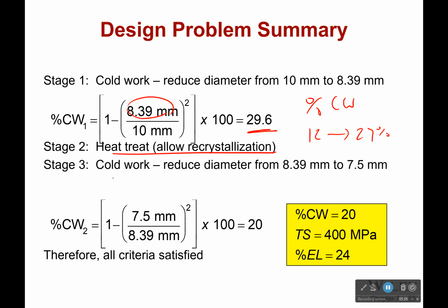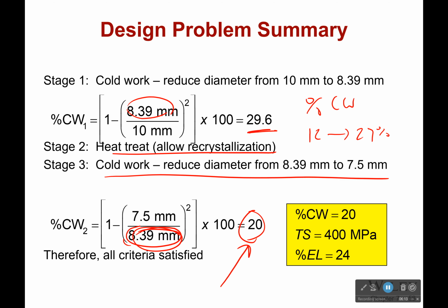And then we reduce the diameter a second time. This time, we're reducing it down to a cold working of 20%, which is perfectly within our bounds. What we did beforehand was solve for this diameter: the diameter that, if there were no cold working before that point and we were to go down to the diameter we wanted, would be right in that sweet spot range. Then we cold work down to this perfect diameter, recrystallize by heat treatment, and then go all the way down again.